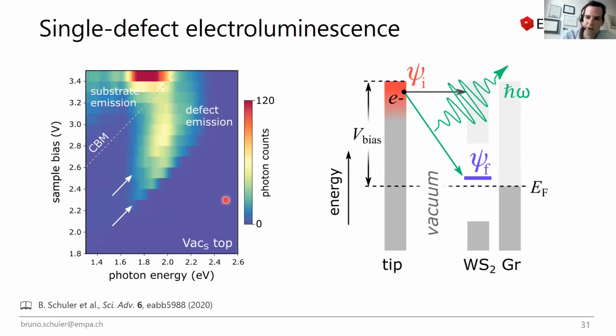Okay, how is this different? I think it's very different from an optical excitation, because there you always study a charge neutral system. In our case, we inject an electron and perturb this heavily into this discrete state. For optical excitation, you would actually do an excitation of your electron at your defect to another state at your defect. And there you would of course expect to see more narrow line widths. But in our case, it's really a combination of some tip property and some defect property.